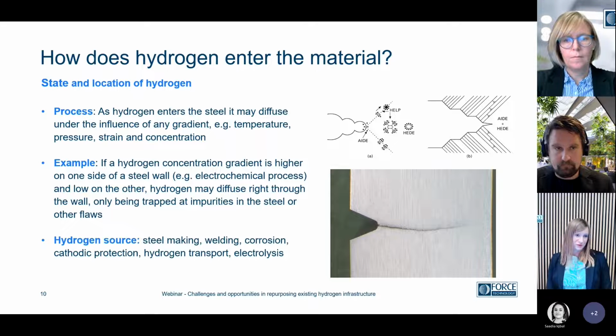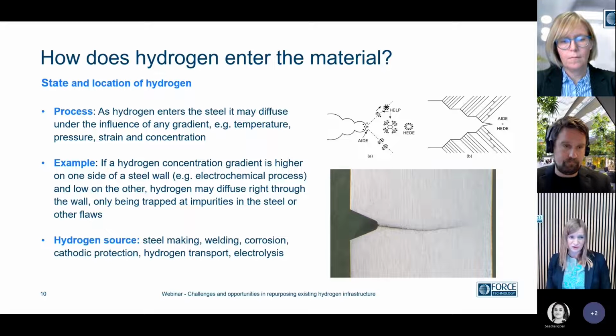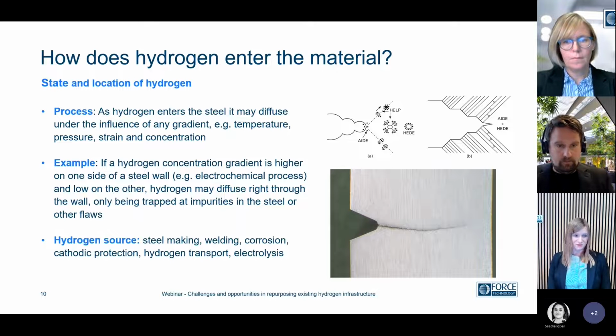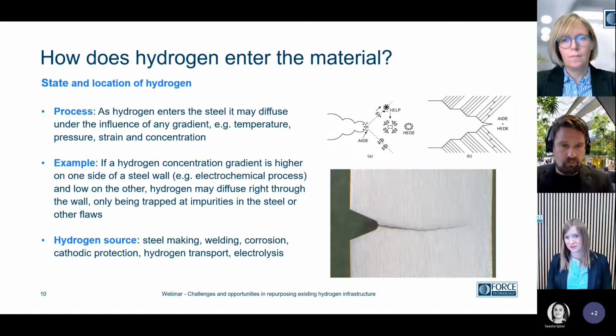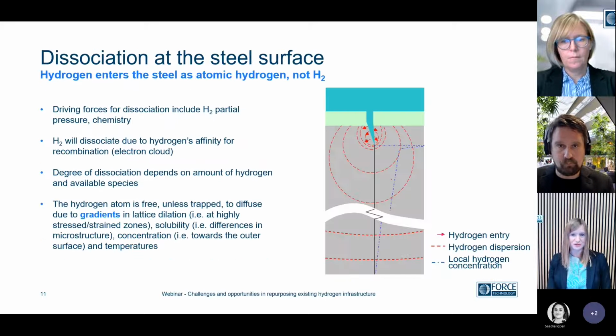Hydrogen sources may be even from manufacturing, steel making, welding, corrosion processes, cathodic protection, hydrogen transport, and electrolysis as service conditions, of course. But in order for hydrogen to enter the steel, it has to dissociate. And that means going from H2 to H, atomic hydrogen. And we have several driving forces for this dissociation.